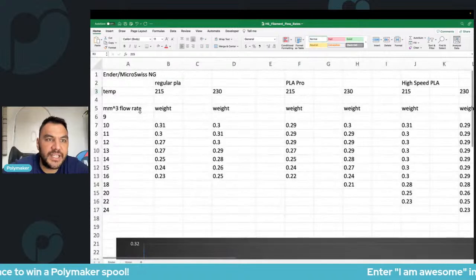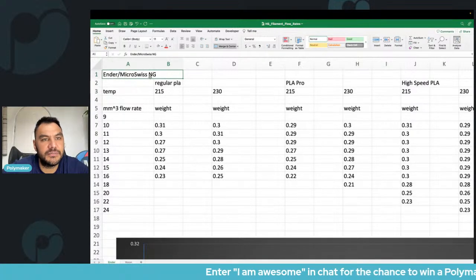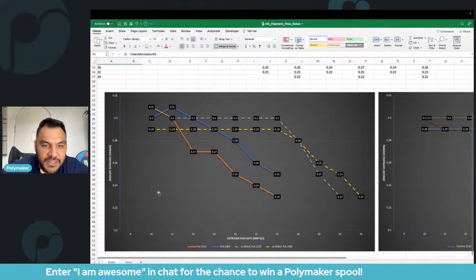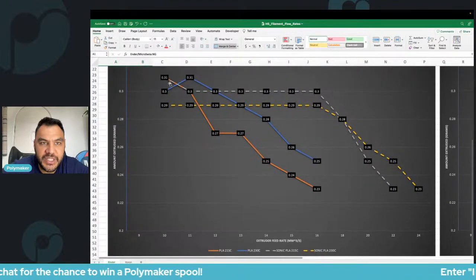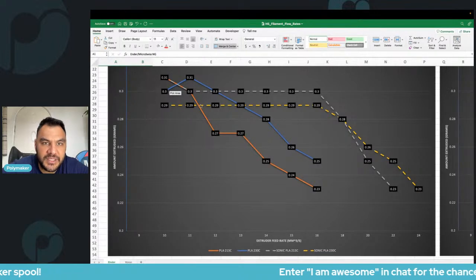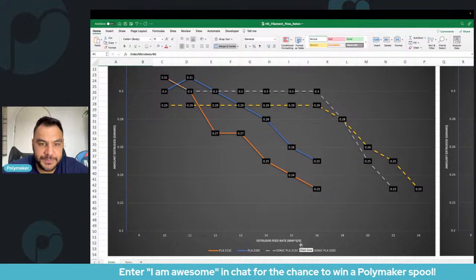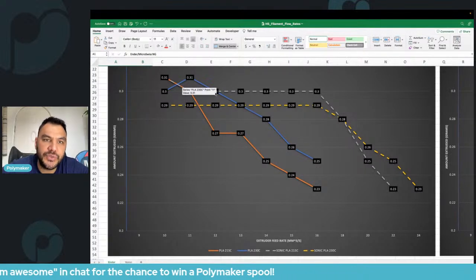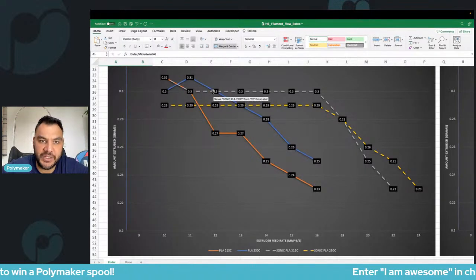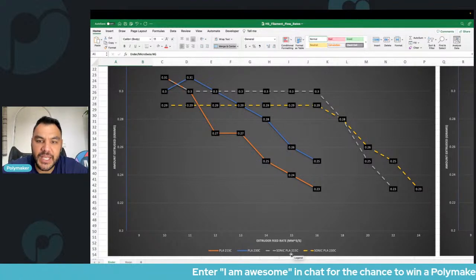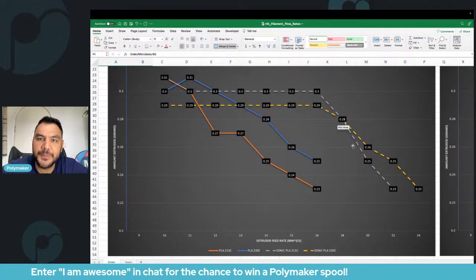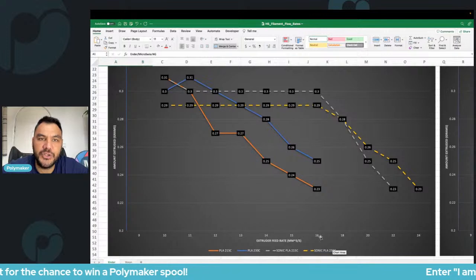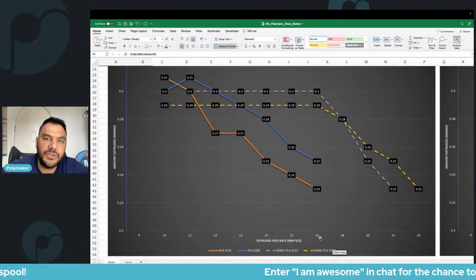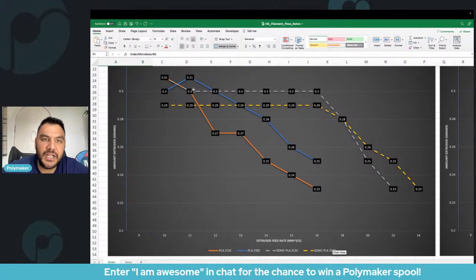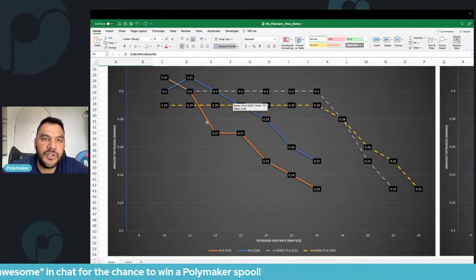Okay, so here you go. This is the data on the Ender with the Micro Swiss NG. This is PolyLite PLA at 215, the orange one. It already dropped significantly at 11 millimeter cube per second. At 230, you are able to increase to 12 millimeter cube per second. But the Sonic PLA, whether it's 215 or 230, is very similar, and you can get up to 16 millimeter cube per second. So you don't double, but you add a good 50% to 60% increase in your volumetric speed on the Ender with a Microsys.